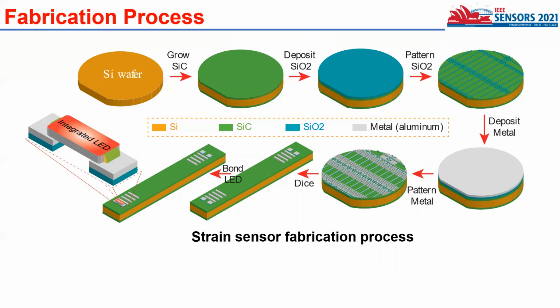top of the silicon carbide and the silicon dioxide layer. After depositing and patterning the metal, the wafer will be diced to form the cantilever, and the LED will be bonded on top of the cantilever using an adhesive bonding method.